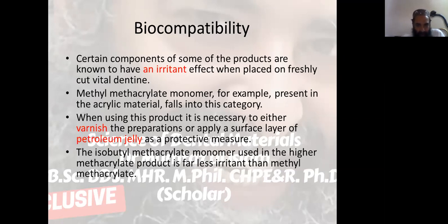When using this product, it is necessary to either varnish the preparations or apply a surface layer of petroleum jelly as a protective measure. The isobutyl methacrylate monomer used in the higher methacrylate product is far less irritant than methyl methacrylate.